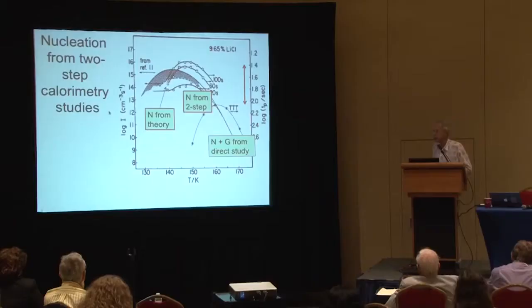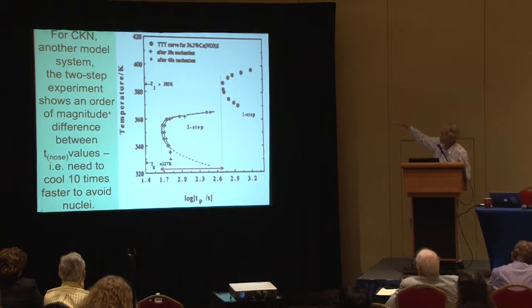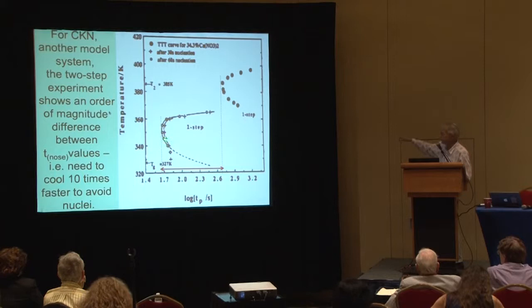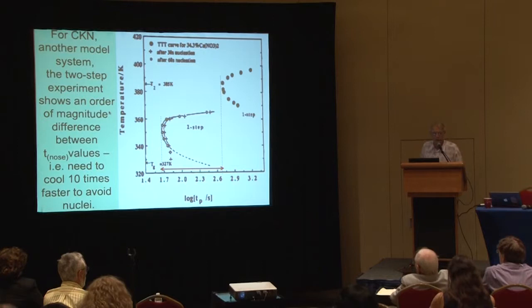So as I say, normal protocols would give you a glass which is loaded up with nuclei. Here's another case of a very simple system without any water in it, just to illustrate that you can do this in more than one system. And here, this is a full order of magnitude. The nose of this appears at a lower temperature and a full order of magnitude shorter in time. So this is a fairly general phenomenon. You can do these measurements easily for many, many different systems and see what you've got.